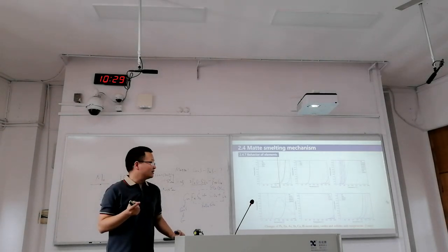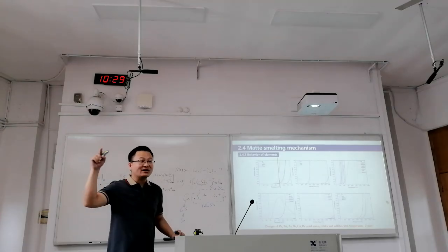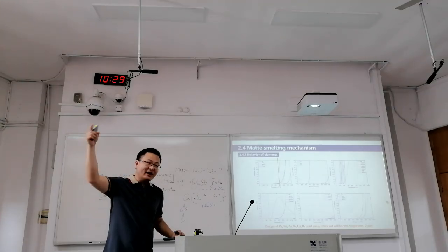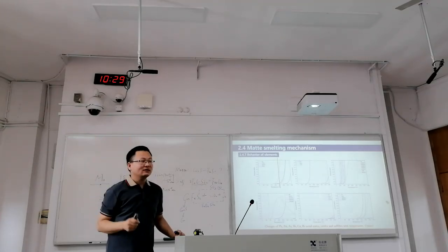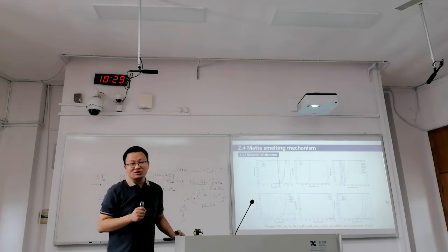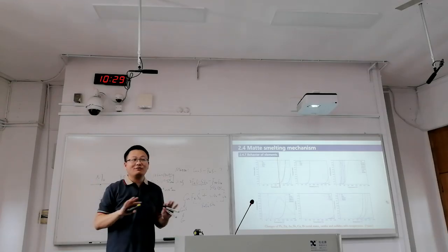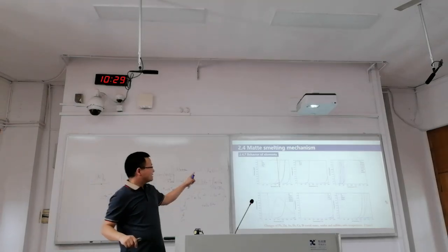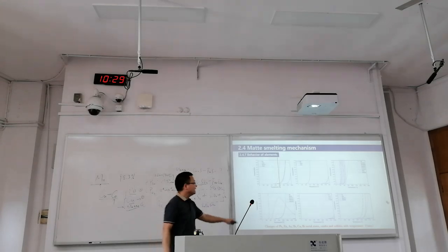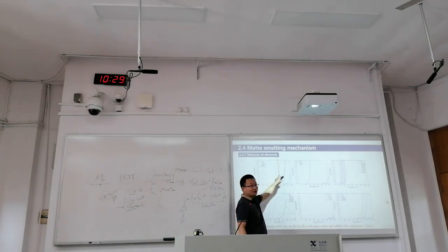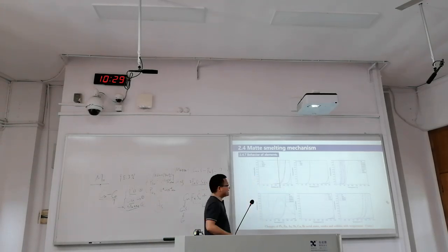But for lead smelting, you are starting with PbS. And when you are adding 100 kilograms of lead sulfide concentrate, we are getting at least 15 kilograms of dust. So that was different because this one is very easy to go to the gas phase.